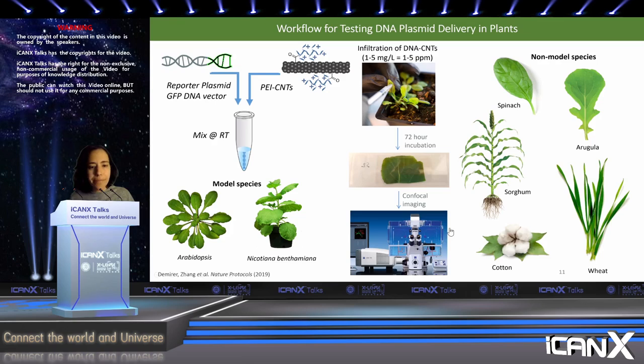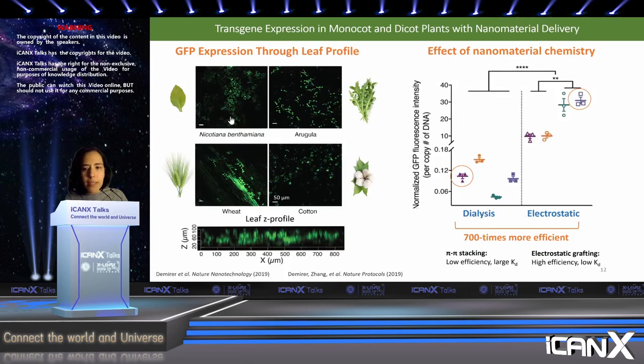on a molecular level. And so here I'm showing some of our results in Benthi, which is a model plant, and in arugula, wheat, and cotton, which are crops. And as you can see here, we observe GFP expression at levels that are about half as efficient as Agrobacterium-mediated transformation, quantified by qPCR. Now, what's interesting is if we look at the effect of chemistry, comparing just dialysis to electrostatic grafting of our carbon nanotubes to our plasmids, what we see is that the dialysis method, which has a high dissociation between the plasmid and the carbon nanotube, does not generate very much GFP expression compared to the electrostatically loaded plasmid. And so what these results highlight is the importance of the plasmid being loaded onto the carbon nanotube with a high affinity for effective expression of the transgenic protein.